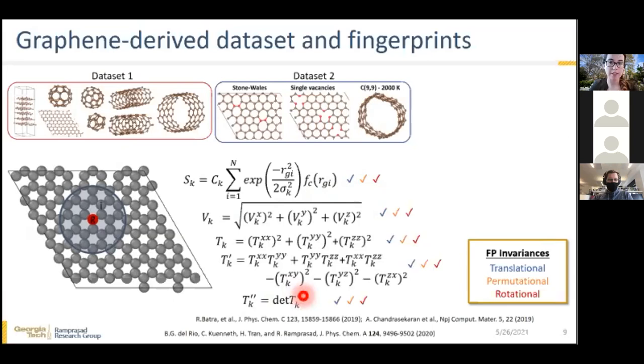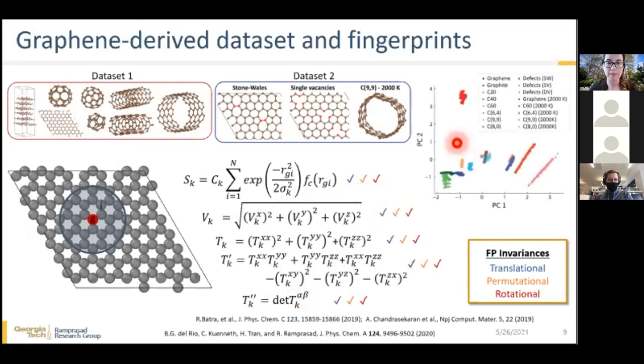Lastly, once we have each configuration fingerprinted, we can perform a principal component analysis here, which shows how the fingerprint features of each type of structures span a large region of configurational space. Now here I am showing the first two principal components, which simply show the two features of the fingerprints which vary the most. And it's nice to see here how different configurations from the same structure are grouped together. And here in blue, for example, are the cases with high disorder. So we can see how they actually are in a slightly different region of space than the configurations at 300 Kelvin, for example.